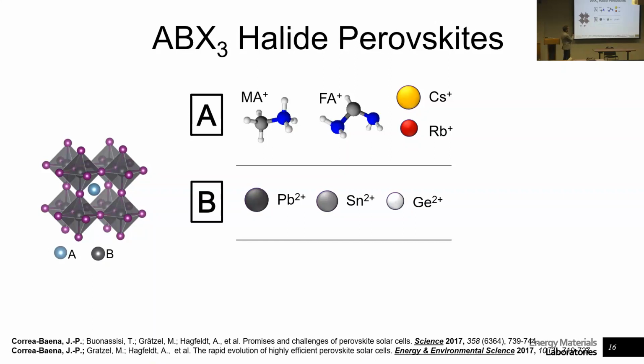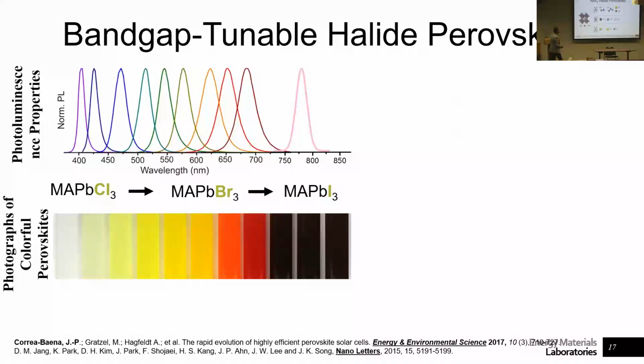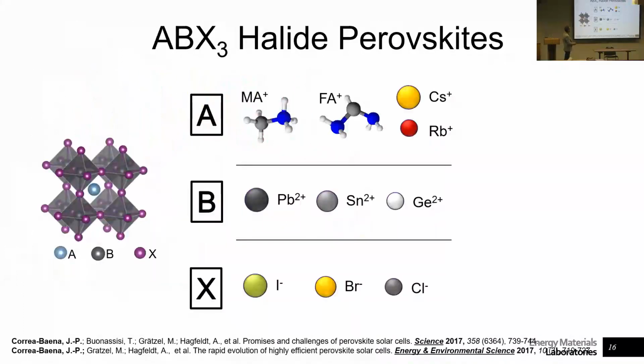For the B side, that's basically that guy sitting here in the middle of this octahedron, that's corner sharing with other octahedra, we can have lead, tin, or germanium. That dictates a little bit of the band gaps of our material. And for the X side, for those corner sharing group sites there, we can have iodine, bromine, or chlorine.